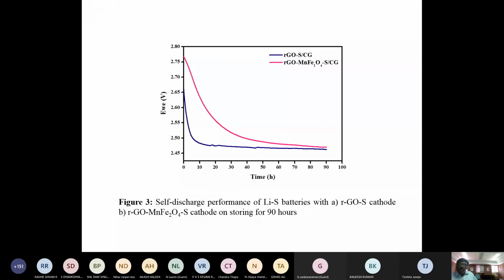We have also prevented self-discharge up to 90 hours. Usually, up to 36 hours, it will lose 30% of its charge. But here we could store the charge at 2.48 volts up to 90 hours. So that is a significant advantage of using our cathode materials.